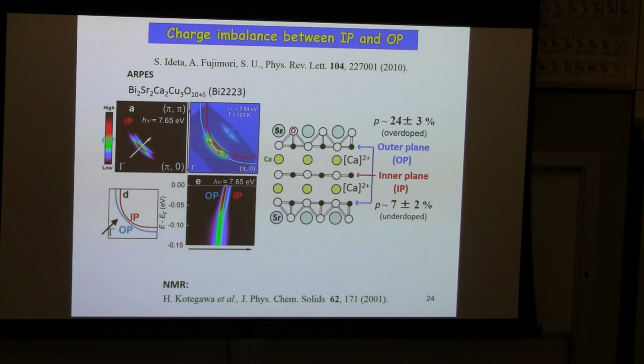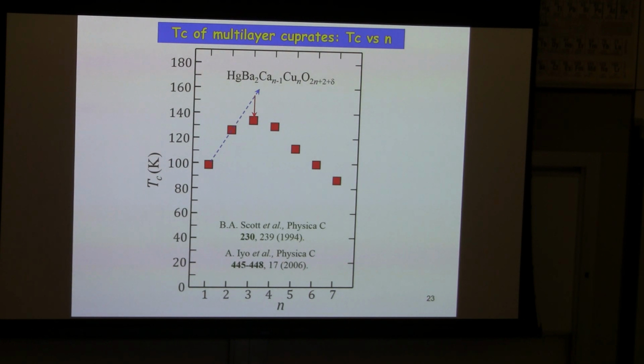Why does it happen? It's very understandable by chemical consideration. You can see that the inner layer is normally sandwiched by calcium ions on both sides. Because calcium ion is 2+ charged, if the copper oxygen plane is sandwiched by 2+ calcium layers, then to maintain the charge neutrality, the copper oxygen layer should be more negatively charged. That prevents the hole density from increasing in the inner plane. Okay, that might be the main reason why TC goes down when the number of layers exceeds 4. And that already happened in the n equals 3 layers.